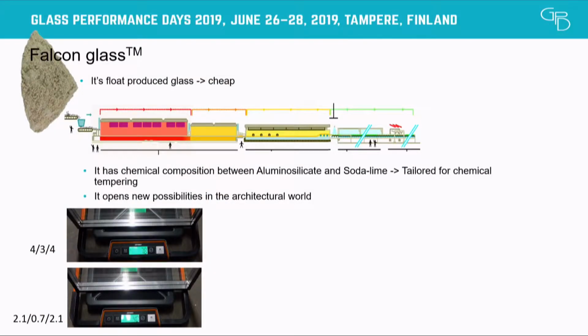And we said, okay, what will happen in terms of weight if we change the glass composition there with all thin glass? This means that our outer panel goes to 2.1, the inner panel to 0.7, and the other external is 2.1. And I'm not sure it's very visible for you, but the balance there is showing that 7.8 is the weight of the glazing at the top, and 4 kilos is the weight of the glazing at the bottom, which means that we have reduced the weight.